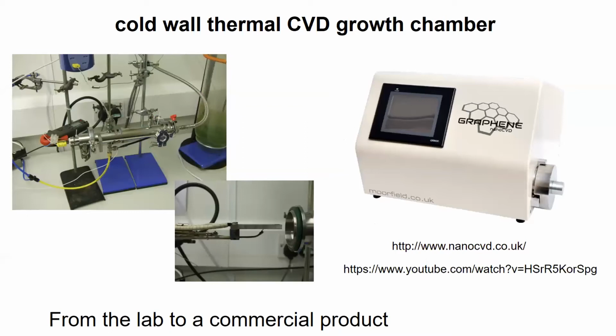You can grow the graphene now in a very similar way to the way that you grow the single-walled nanotubes. So I said that you would have an oven system, and you would have a carbon source, and you would have nanoparticles for the nanotubes. Okay, all we're going to do here is we don't want to grow a tube from a nanoparticle, we want to grow just a flat sheet. And what we do is we use a metal catalyst, but it's in a sheet form. And if you use particular metals, you can grow just one single layer of the graphene. Some of the metals will promote multi-layers, but if you use something like copper, you will grow just a single layer of graphene. And this is really useful now because dependent on how big your copper sheet is, you can grow large volumes of graphene.